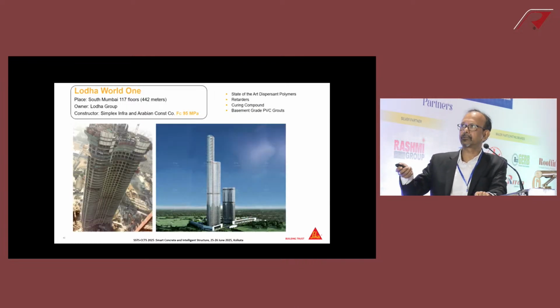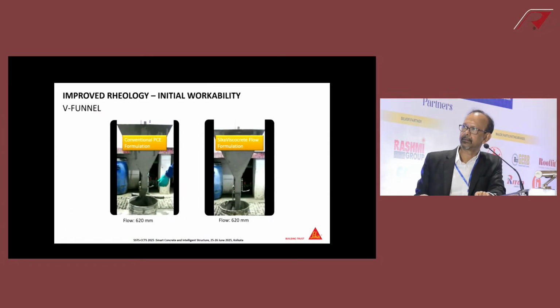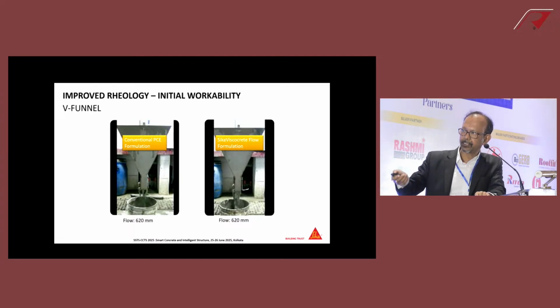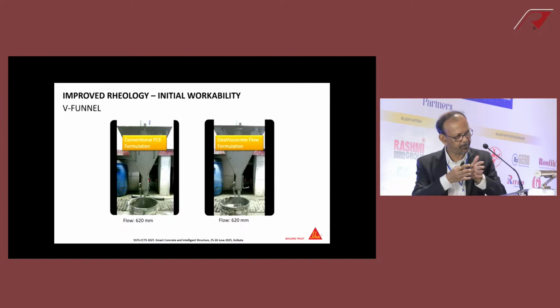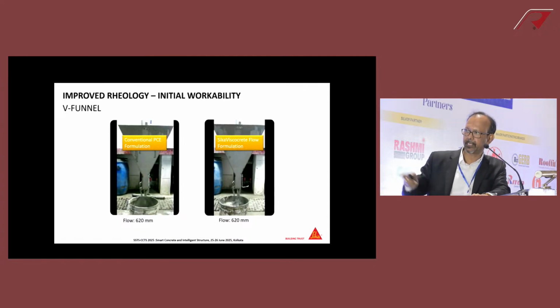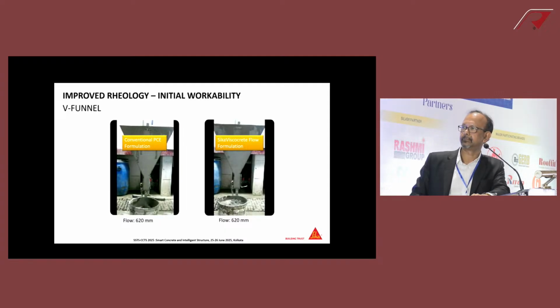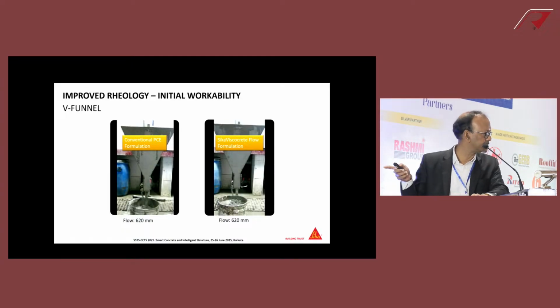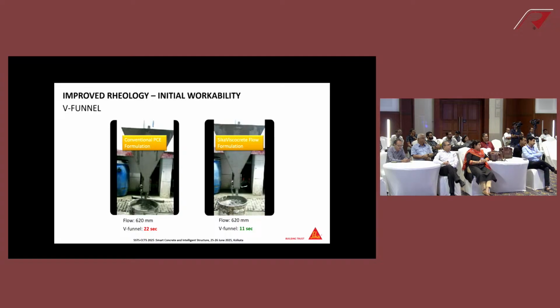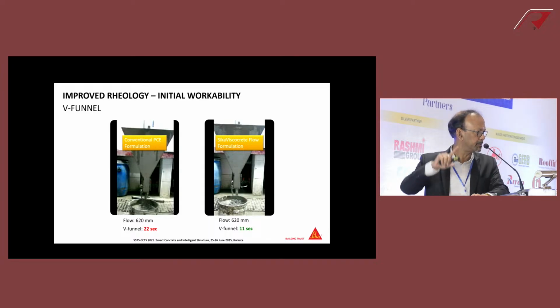So you see, this is what was used even up to 95. This is Lodha World 1. Just to give you an idea about conventional concrete versus this same flow, but the time taken to fill it up. So you can see the time difference. This is the rate of flow, or rate of ease of flow. So 22 seconds, 11 seconds. That translates into the flow through the concrete pipe, aided by the pump, at whichever level you want to take it.